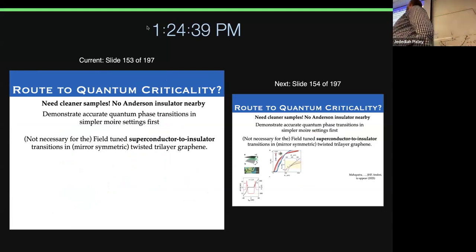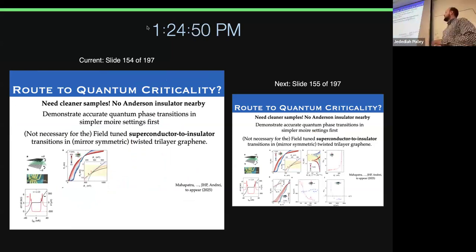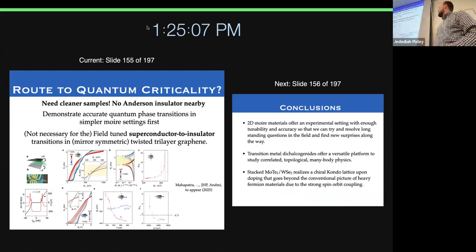So we know superconductor insulator transitions from a great amount of work in the past in 2D materials. Here I want to think about this in a moire material. So with Eva, we've been thinking about twisted trilayer graphene, mirror symmetric twisted. It has the largest Tc out of all these moire superconductors. By applying a magnetic field, they can see really beautiful superconductor to insulator transitions. This is out-of-plane field. And they can also do in-plane field, and they can then do basically beautiful scaling collapse.